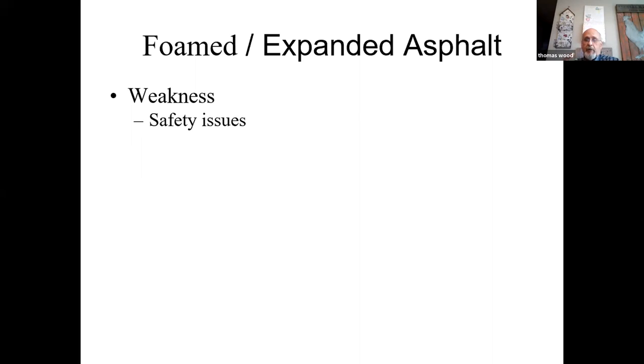So I'll go back to when I do my surface treatment classes. At room temperature, liquid asphalt binder is a semi-liquid. You can actually take a little metal tin and fill it full of asphalt binder and let it cool to room temperature. And if you turn the tin on its side, over time it'll slowly creep out. It's really not usable. So there's three ways to make it usable. We can heat it up. And what we're doing when we heat it up is we're lowering the viscosity so it flows.